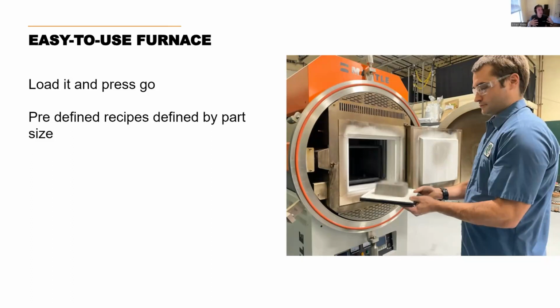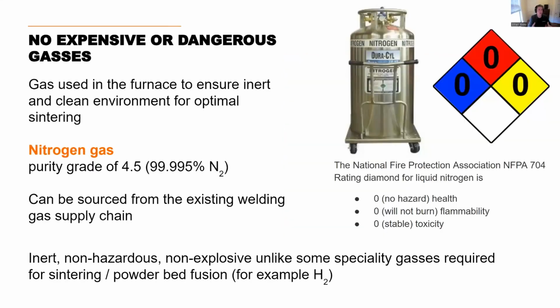The furnace is what's called a vacuum furnace, which means it's pulling vacuum before sintering. The reason for this is because, as you probably know, with things like welding or other temperature processes, when things get very, very hot, they tend to oxidize very quickly. So in order to inert this environment, and ensure we have a very clean sintering environment, two things are happening here. First, we're going to pull a vacuum to remove all the air out of that chamber, and then we're going to flood with an inert gas. The gas that we use in our process is going to be a nitrogen gas.